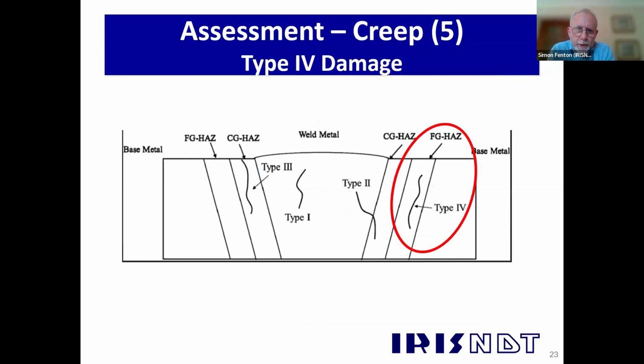So moving on to welds now. This is a schematic of the convention that's used. It's a German convention to describe the development of cracks in different positions of the weld. So in the centre there, we've got the weld metal. On the far left and far right, we've got the parent material, the base metal. And then in between, we've got the heat affected zone. Pete talked about this earlier. But what I've done there is split that into the fine-grained heat affected zone on the outside and the coarse-grained heat affected zone on the inside, closer to the weld.